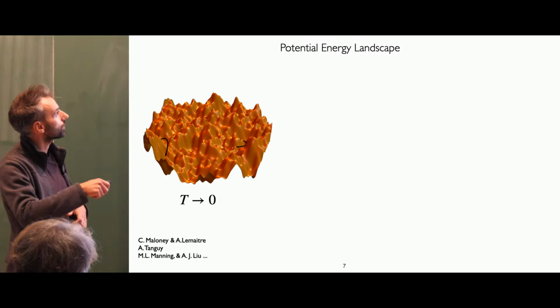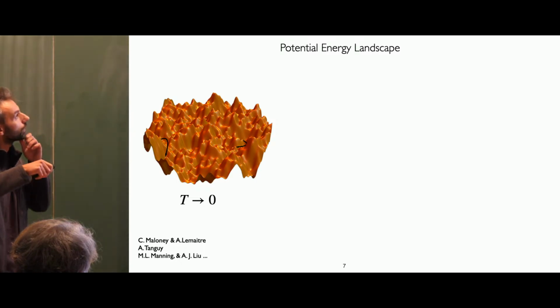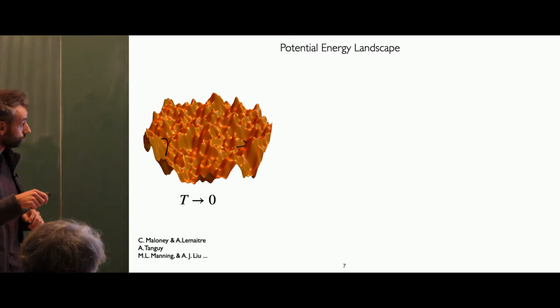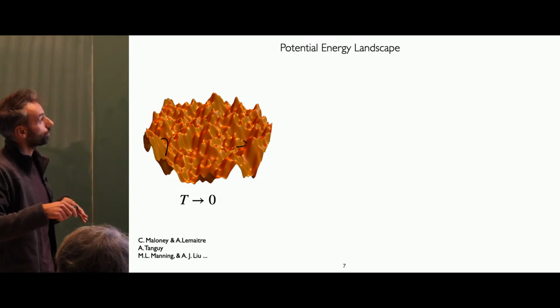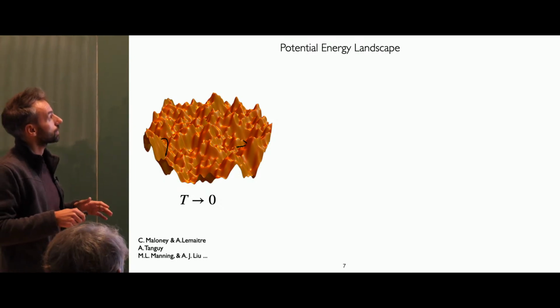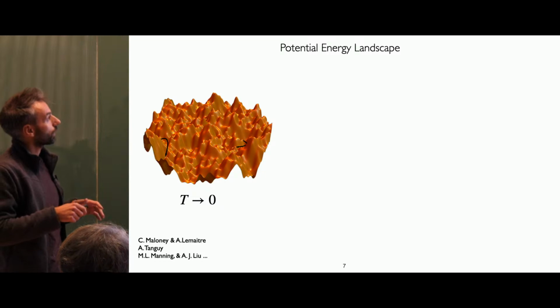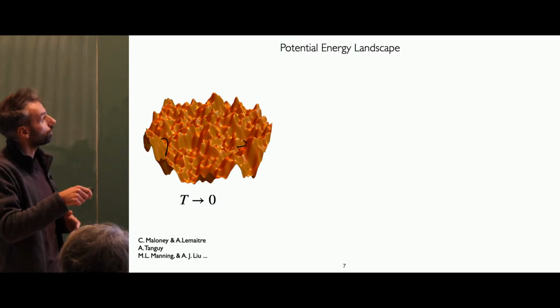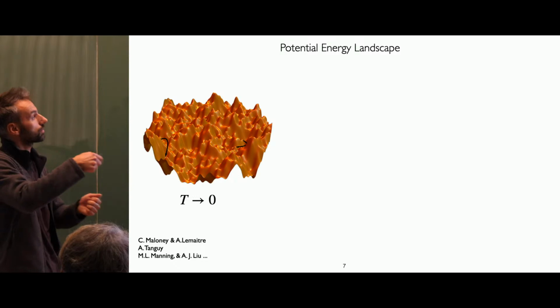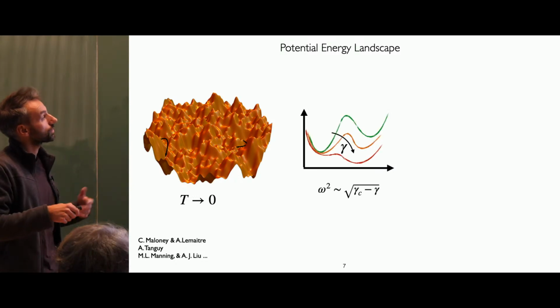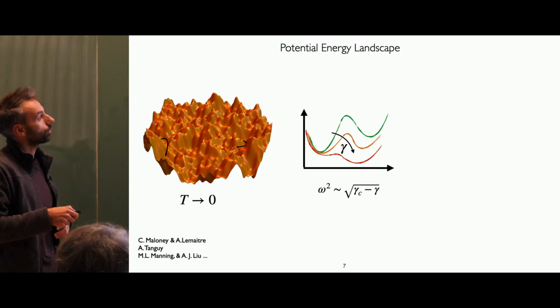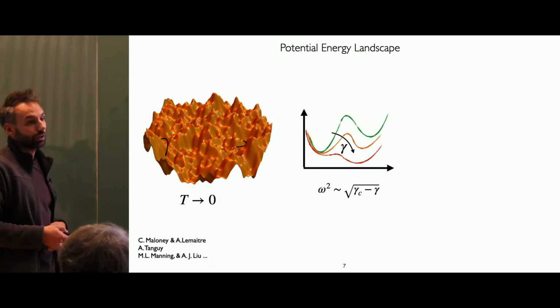And so my tools are based mainly on the potential energy landscape. So I will think more about zero temperature, so I will not even have thermal activation. But since I'm deforming my system, I can still hop from one minimum to the other by applying some stress. And if the stress is large enough, if the deformation is large enough, at some point the system will become unstable and relax to a new minimum.